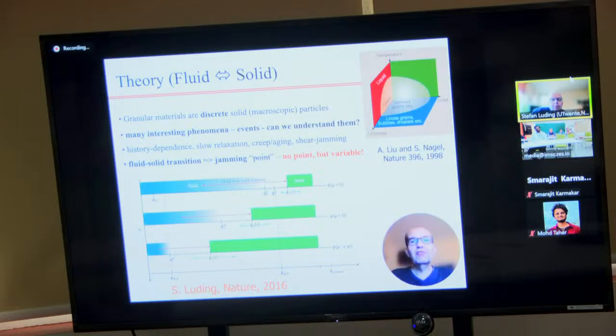Now, in order to formulate this theory, which I mentioned, which I showed you some preliminary results already, we have to appreciate one more thing, and that is the jamming diagram, but in event-related form. Note that many interesting things are happening. So we have history dependence, we have slow relaxation, we have creep, aging, we have shear jamming, as I showed, and we have the jamming point, which is not a point, it's a variable. This has to be appreciated, and only then can we formulate this general theory, which includes the events, their probabilities, and which includes jamming, unjamming, fluid-solid transition, gas states, fluid states, and solid states, as it's so interesting for granular physics.